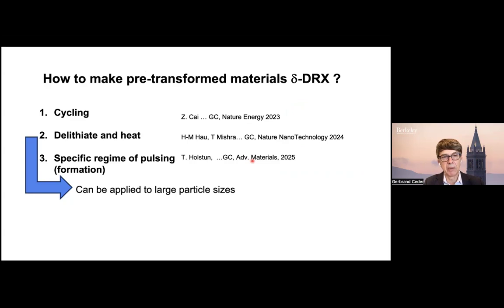But a challenge for us to make this practical was how could you induce this material? You know, our original work and that from Guiying Chen at LBNL showed that you could certainly get this with cycling, but again, it's not very practical. So we've come up with a few different ways, and I'm showing here 2 more that have just been published. One is you can actually delithiate the material and slightly heat it, and it will transform to delta. That may or may not be practical because you have to take lithium out of the material and then re-lithiate it before you put in a cathode.